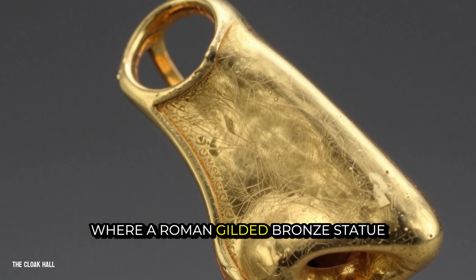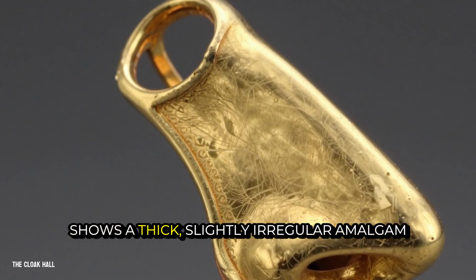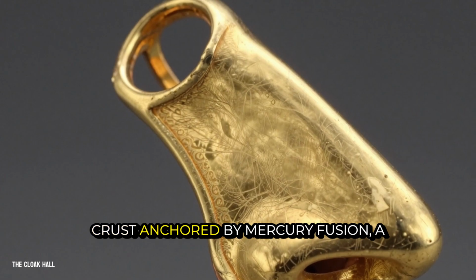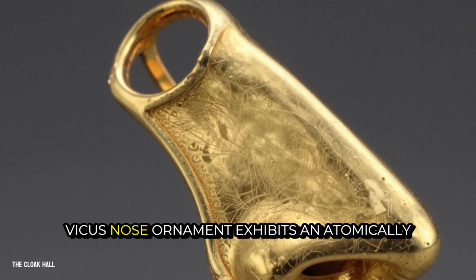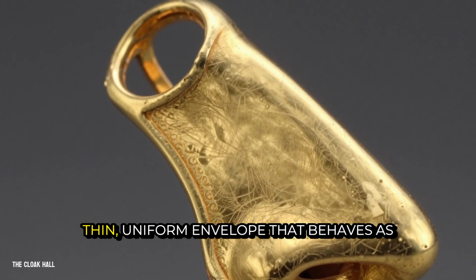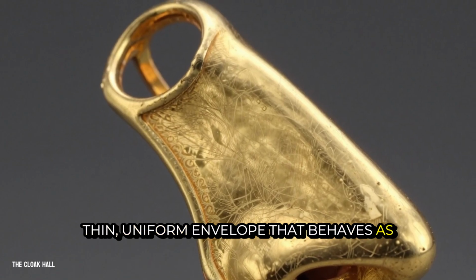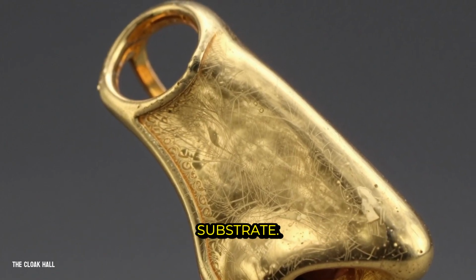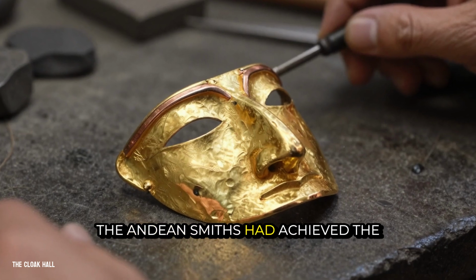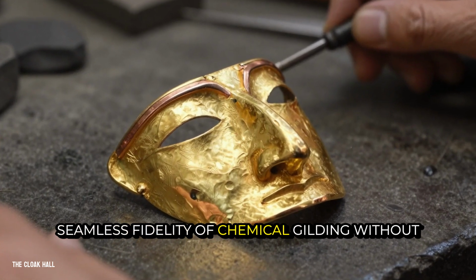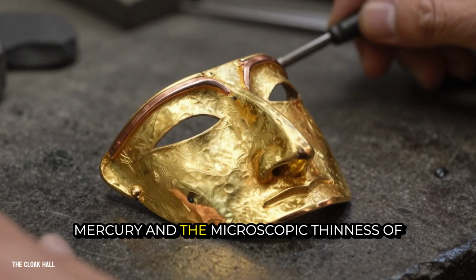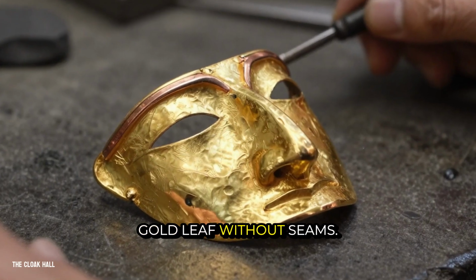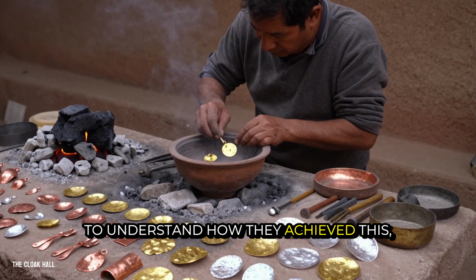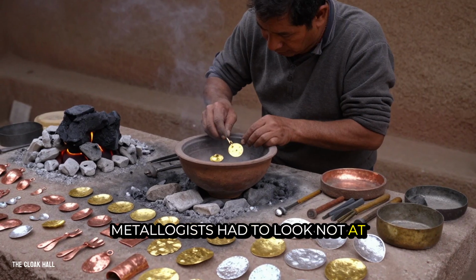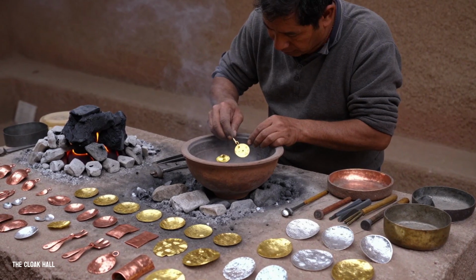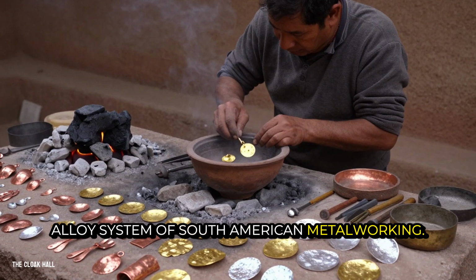Where a Roman gilded bronze statue shows a thick, slightly irregular amalgam crust anchored by mercury fusion, a Vicús nose ornament exhibits an atomically thin, uniform envelope that behaves as a single metallurgical unit with the substrate. The Andean smiths had achieved the seamless fidelity of chemical gilding without mercury and the microscopic thinness of gold leaf without seams. To understand how they achieved this, metallurgists had to look not at pure metals, but at the foundational alloy system of South American metalworking.